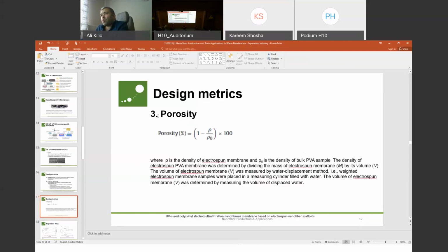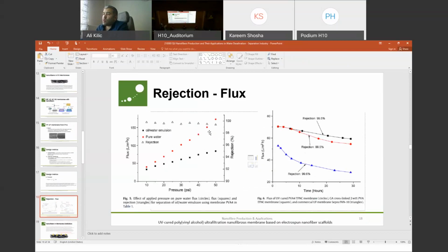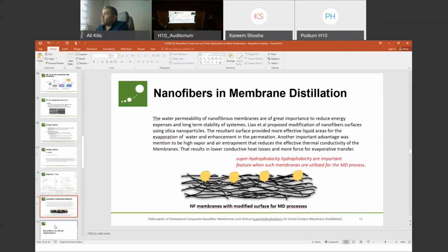So we do have high porosity compared to other membranes. This porosity allows the permeation of water, which you can see here actually. This is from a resource also. As you see here, for regular membranes, flux is quite low. And if we go for nanofibrous structures, even with very similar rejection rates, you can increase the flux up to 50%. This is quite a good number, I believe. This is quite a nice improvement to produce the membranes. I believe compared to traditional systems, this is going to work in the coming years. I strongly believe that.